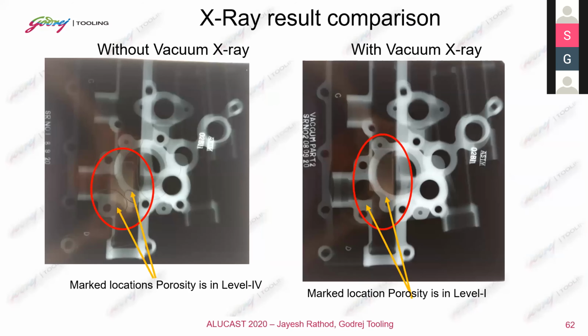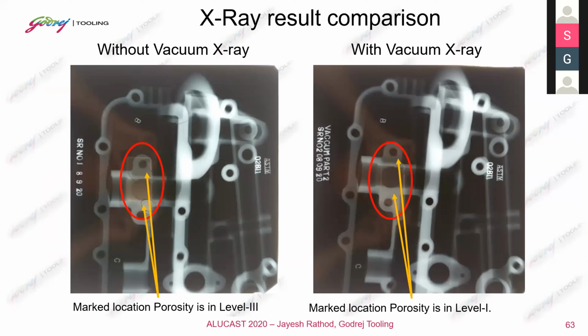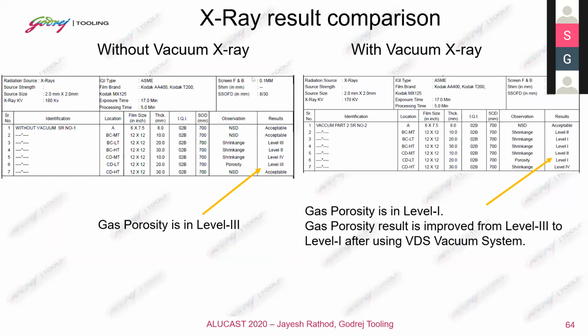But only one plane section is not sufficient, so we went for an X-ray study. And there also we have seen a marked improvement. We can see that level 3 porosity can be converted to level 1, which was quite acceptable to our customer. So we could see in many areas, those were CTQs, and we were able to achieve level 1 porosity.